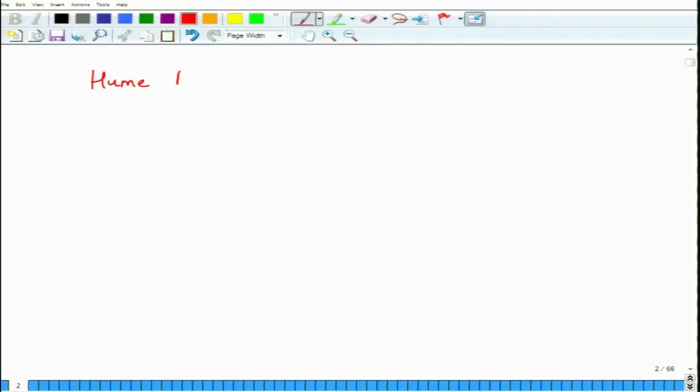size. There are some rules for substitutional solid solutions, which were called the Hume-Rothery rules, which said that it depends upon the size difference and the valence difference. If you want to make a substitutional solid solution, extensive solid solubility is permitted only when the size difference is less than 15%, the valences are nearly similar, the crystal structures are similar, and the electronegativity difference is very small. There are certain violations, but by and large these rules are followed.